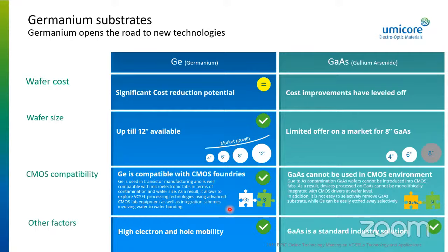So, if you think about it, germanium is a CMOS compatible material. It's used in a gate stack. It's level 2, so in terms of contamination requirements, it's absolutely fine with CMOS foundries. And then in terms of wafer diameter, as I said, you can go for 8-inch and 12-inch, which makes it CMOS compatible. So there you can envision certain things like you can process your wafer in a CMOS foundry, or you can do integration with silicon drivers at the wafer level. So there are interesting things that can arise from there. And then there are other factors, of course, to be fair, gallium arsenide is a standard industry solution these days.